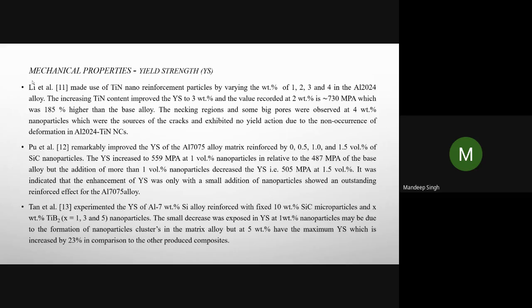So here Li and others made use of TiN nano reinforcement particles by varying the weight percentage of 1, 2, 3, and 4 in the Al2024 alloy. The increasing titanium nitride content improved the yield strength up to 3%, and the maximum was recorded at 2 weight percent, that is 730 megapascal, which was 185% higher than the baseline.